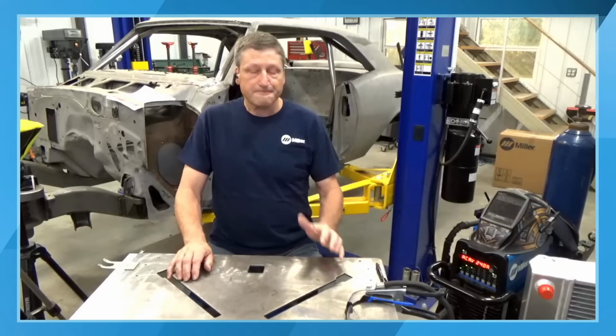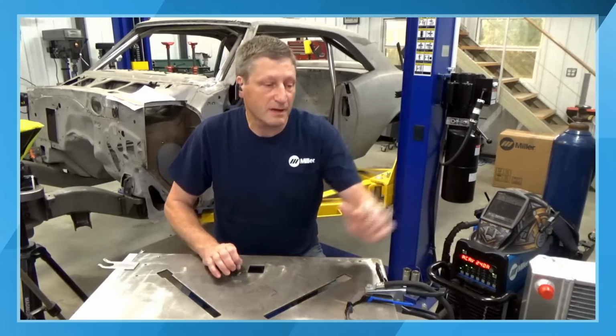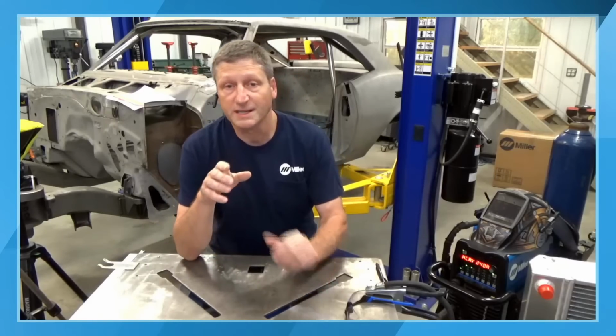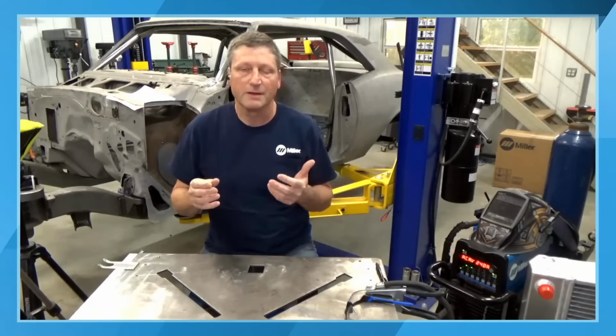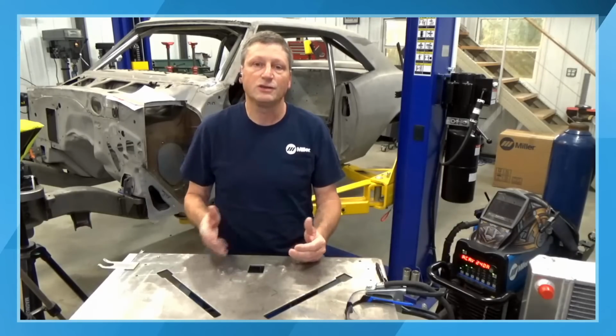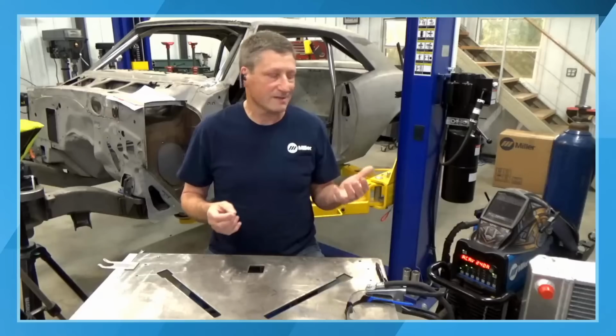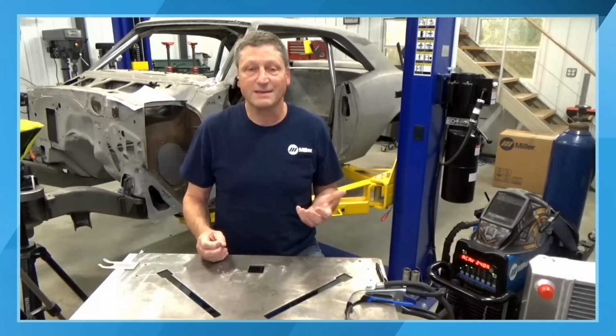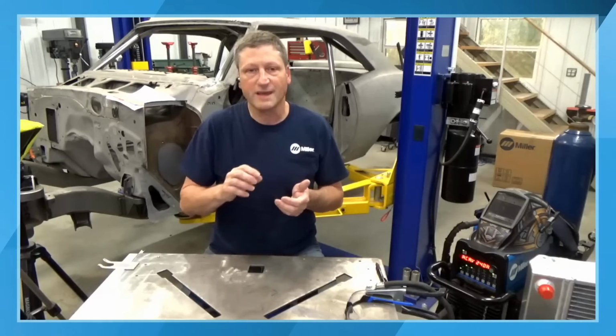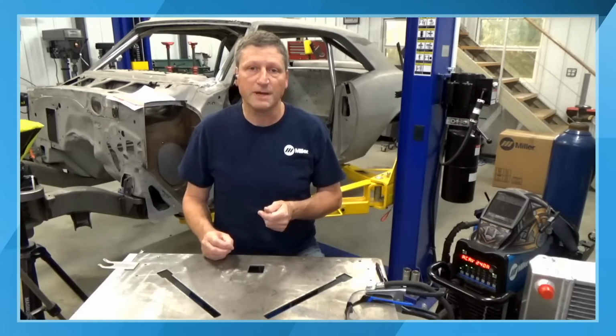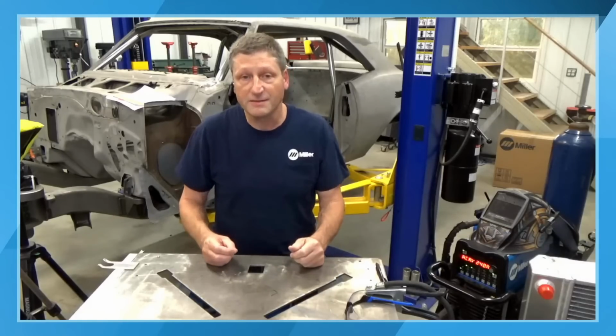So, some examples. I guess we could talk about annealing too. If you have an issue with bending it and you want to anneal the aluminum, you could do that as well. Annealing is just softening the aluminum, and you can do that with an acetylene torch or any type of heat source that gets it up to that level where you're removing that higher tensile strength of the aluminum.